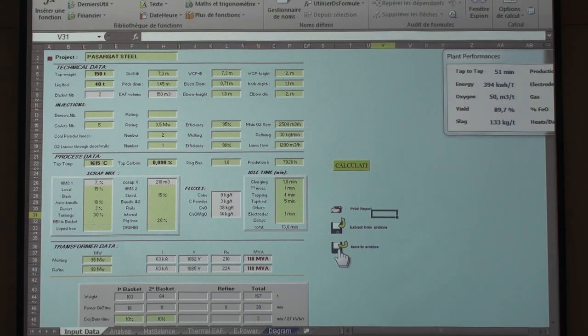Okay, production time is given by the customer. Scrap mix is given by the customer. And charging time, you have to be in reasonable conditions. One minute for basket charging is good performance. Usually nowadays we don't need to interrupt the process for temperature measurement. Tapping, again, it's average tapping. When the tap hole is new, then tapping time is longer than when the tap hole is old. So here in this case, it's all the time the average tapping time.